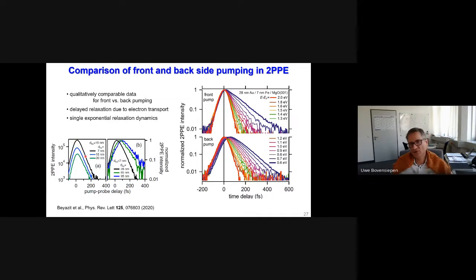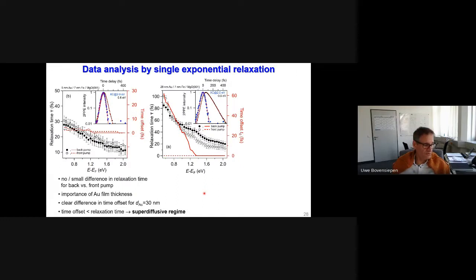That means the electrons relax already in gold and we have less hot electrons to inject into gold. If we keep the iron layer thickness constant and we change the gold layer thickness, then what we do is basically modify the relaxation and the transport, which we can see here in the shift of the maximum and these slopes. This is what I will discuss in detail now in the last few slides of my talk.